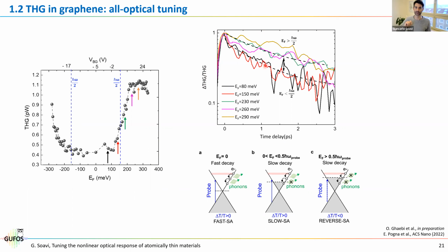What is interesting here is that the dynamics are different depending on the Fermi energy or the Fermi level. In particular, where the Fermi energy is small, 80 or 150 millielectron volt, the dynamics is faster compared to the case where the Fermi energy is large. So you see the curves here at the top. And now we have an explanation for this one. This is another paper that we published recently in ACS Nano. And the reason is the following. You can see it from this sketch.